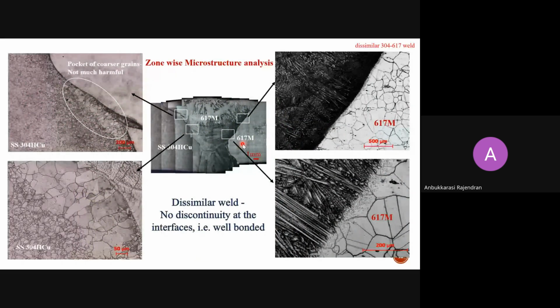So this is another micrograph from the dissimilar metal welding, which was done by myself for my postdoctoral research. Again, it is a montage image of the weld interface. It contains nearly 100 small optical micrographs. Then, in our region of interest, we took images at high magnification, so it reveals the grains clearly.